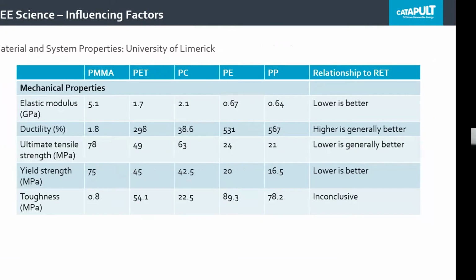They also measured mechanical properties using normal tensile tests, so modulus, ductility, tensile strength, yield strength, and toughness, and generally found that a lower elastic modulus and lower tensile strength is actually better for rain erosion resistance than higher stiffnesses, higher hardnesses. And the better the ductility or the elasticity is also good.